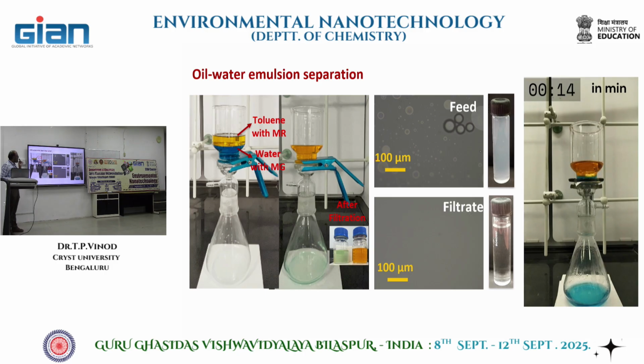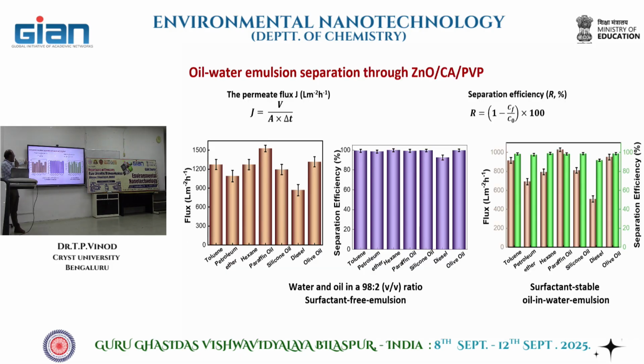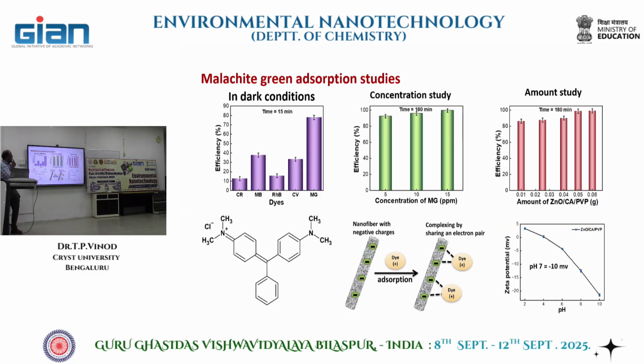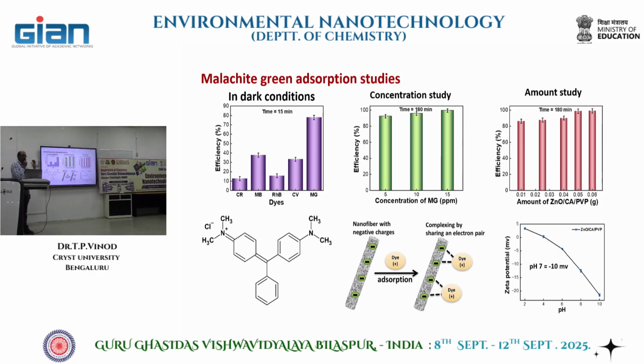And then we tested, like, if you just keep it like that for hours, it should not mix again, right? So we were able to actually hold it like more than 4 hours. Even after more than 4 hours, it's not coming down. So like it's very simple. You have an oil-water mixture, take it and then pour through this membrane. Oil is separate and water is separate. So we could use it for oil-water separation. And then there are like some technical parameters about like how much is the flux permeation, some calculation about how efficient this system is. Okay, that's one thing. And then we used it for oil-water separation.